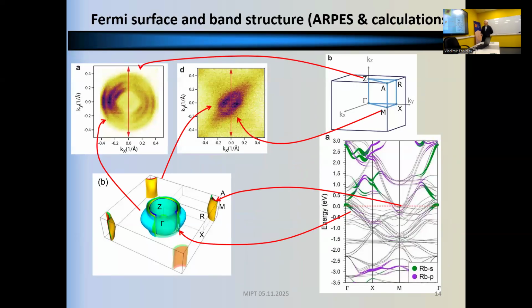let me move to band structure. The band structure is actually usual for all other 122 superconductors because it consists of two cells of 122 type, which are usual iron-based superconductors. So it's just a twice bigger lattice cell. In ARPES and in calculations, there is the usual multi-band structure with inner hole bands, multiple coaxial cylinders, and some electron bands at the corner of the zone. The electrons which form the superconducting pairs come from these bands, and their multi-band nature promotes the S plus minus pairing by spin fluctuation.